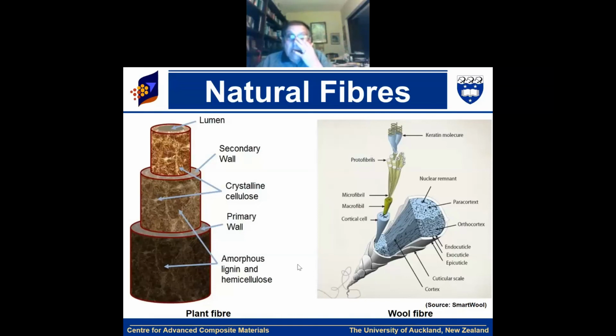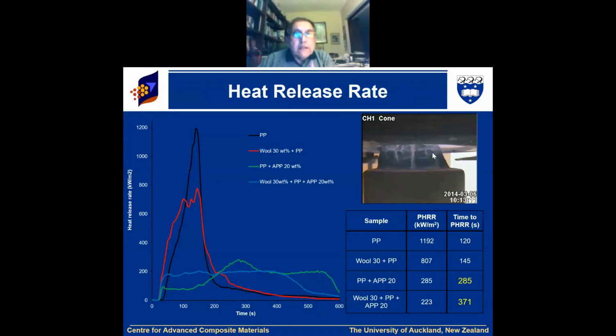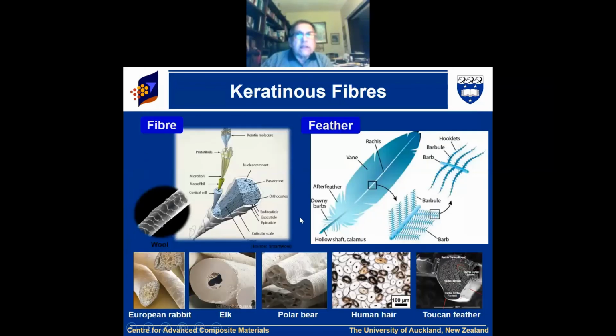Whereas if we look at wool fiber and other keratinous fibers, you have got a lot of keratin, which is a protein material. And whether protein is fire resistant, we thought whether we can use that property to diminish the fire chances. When we used wool at 30%, the peak heat release rate dropped a bit, but it really was not that effective. So we mixed wool with APP, and the APP percentage could be reduced very much, because APP is very expensive. If we could reduce APP, it was an achievement. But we are not entirely happy because wool was not working. So we thought we should look at other keratinous fibers as well.